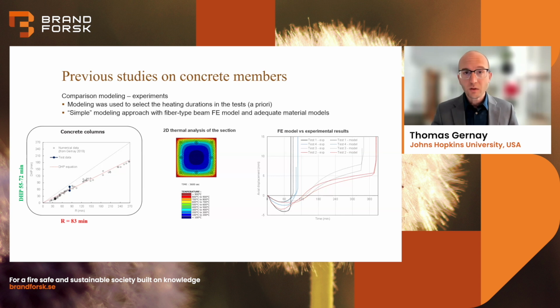In that study, numerical modeling was used a priori before the test in order to inform the durations of the fires that we would apply in the furnaces. And then again, at the end, to compare the evolutions of deformations with time. And we found a good agreement between the numerical study that was conducted before and the experiments in terms of fire resistance rating, as well as in terms of predicting a failure in cooling.